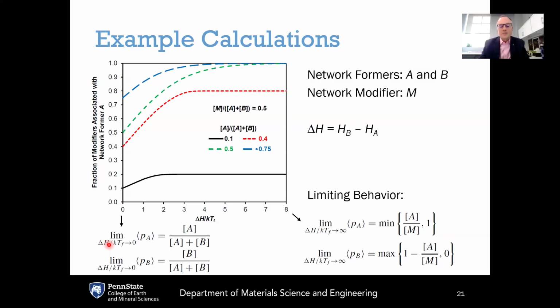So in other words, at this limit, we're completely governed by entropy. So the probability of associating with network former A is just a function of the composition of how much A is there relative to the total amount. So the concentration of A over the total concentration of the network former is A plus B. And likewise for the probability of B. So this would be the entropic limit here.